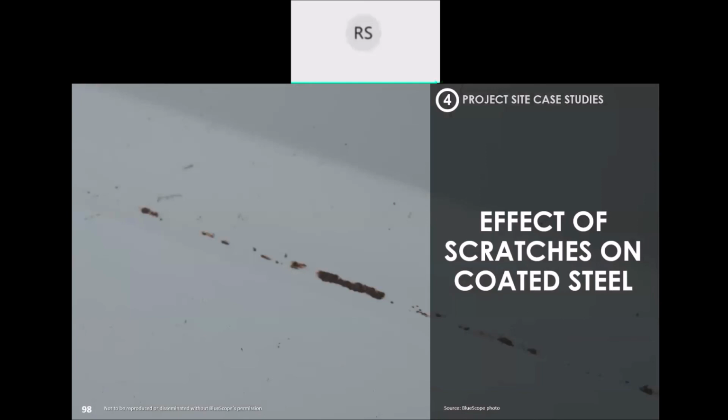In this case, this scratch itself, even though it has actually shown corrosion, this is after 12 years. And the scratch itself is actually kind of minor, right? After 12 years, you actually don't see any penetration through this roof, right? Those are the things that we can collect from this project site case study to give back more value to, for example, designers and project managers, so that we can give much more confidence about a certain product or specification, so that they will make the right action, or so-called informed decision.